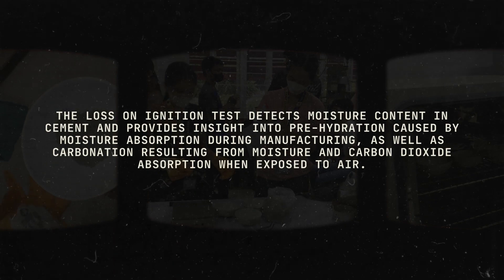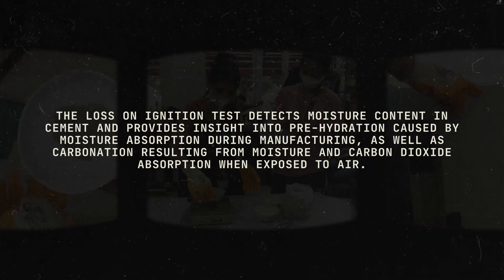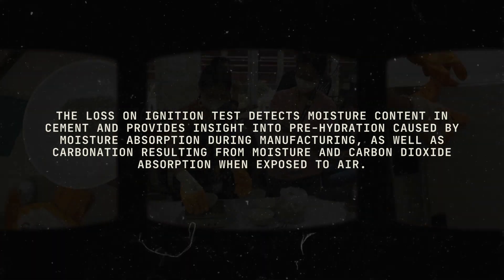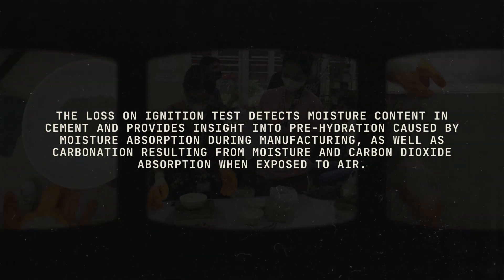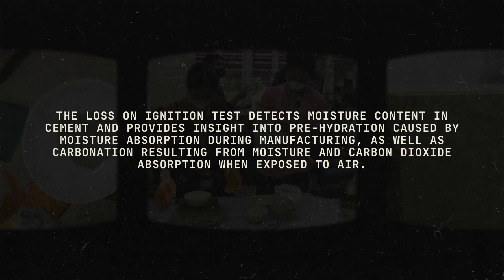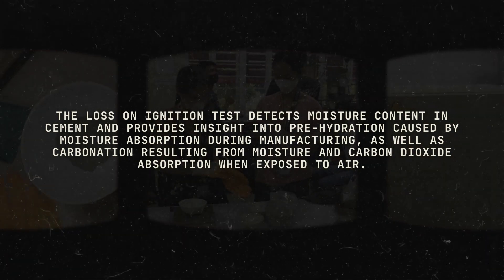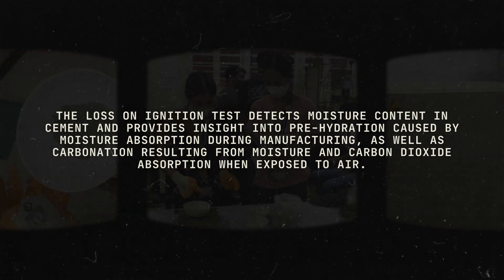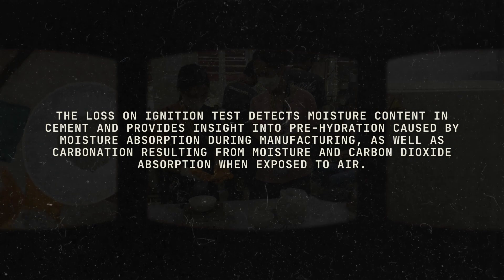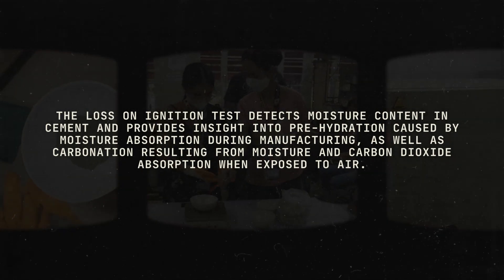The loss on ignition test is a very simple test which indicates moisture in the cement. The loss is an indication of pre-hydration, which results from introduction or absorption of moisture during manufacture, or carbonation, which results from the absorption of moisture and carbon dioxide in exposure to the air.